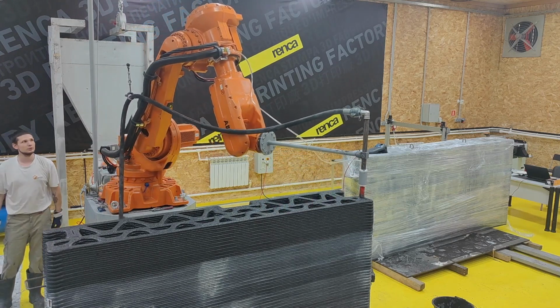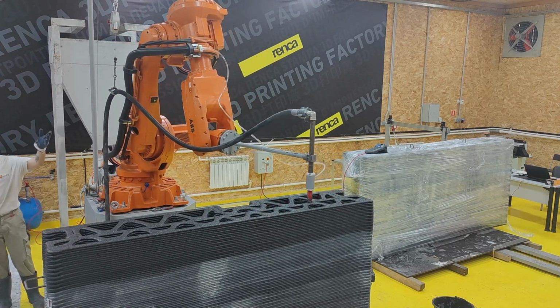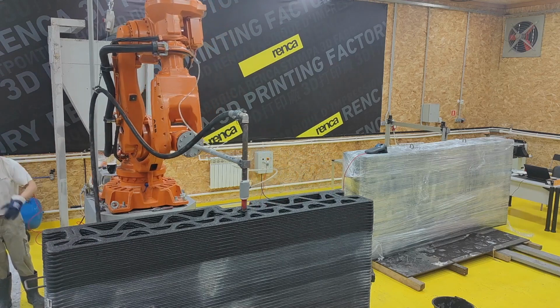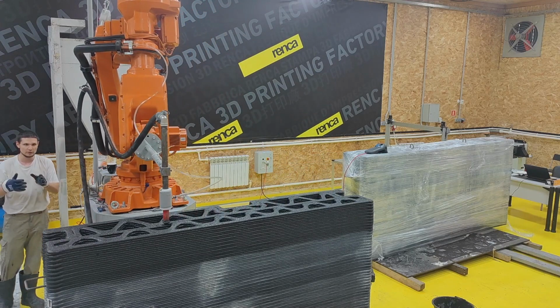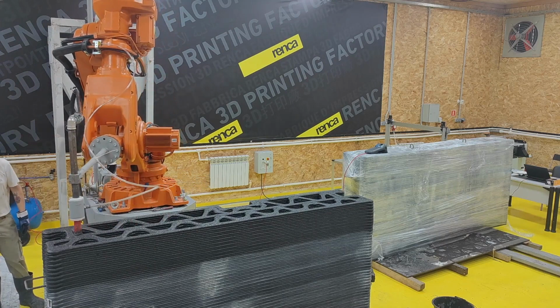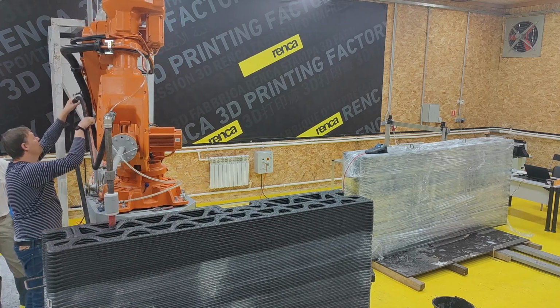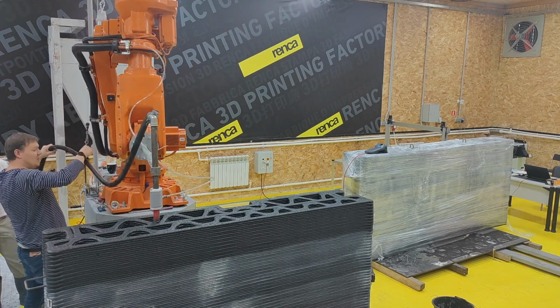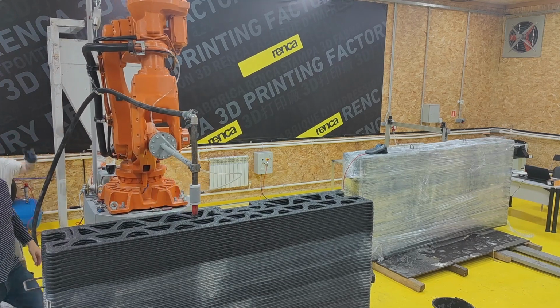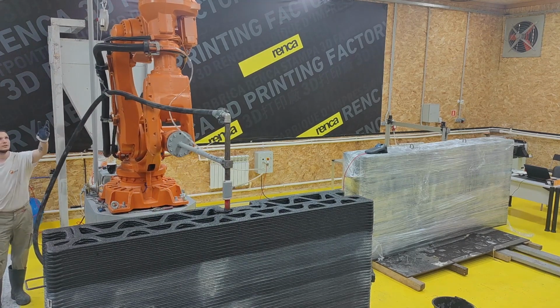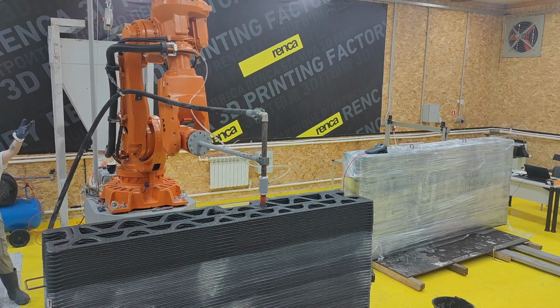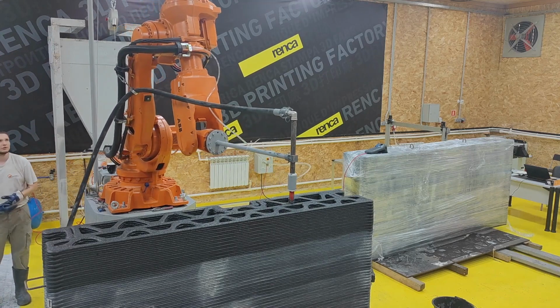It's a chemical bonding between layers. So even if we stop one day and we decide to continue the next day with a fresh layer, with a fresh geopolymer, we don't need to prepare the surface. We don't need any glues or whatever. The adhesion will be perfect and it will become a monolith. And also it has a very high strength, above 40 MPa and more. And it has a fast setting.